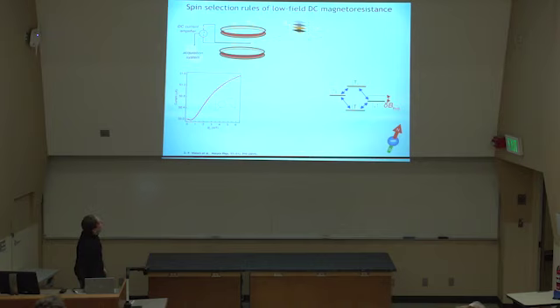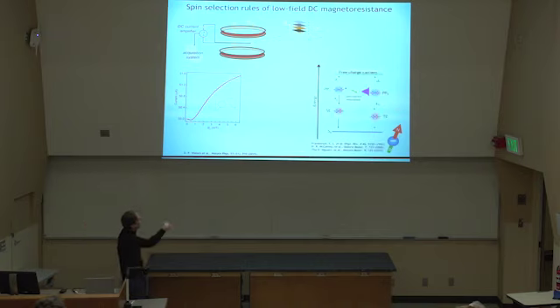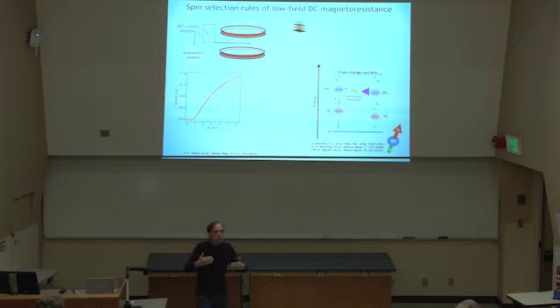And so you see how these non-equilibrium processes allow you, by changing, in this example, permutation symmetries, and you know, if you look at the energy scales of these shifts, we are talking about nano-electron volt to maybe lower micro-electron volt range, so orders of magnitude below the thermal energies, but that completely allows you to switch permutation symmetry ratios and therefore your recombination rates.